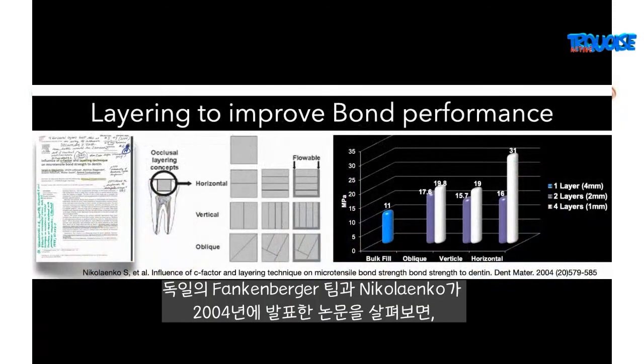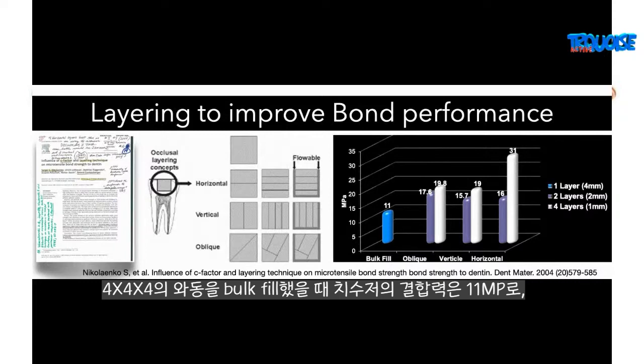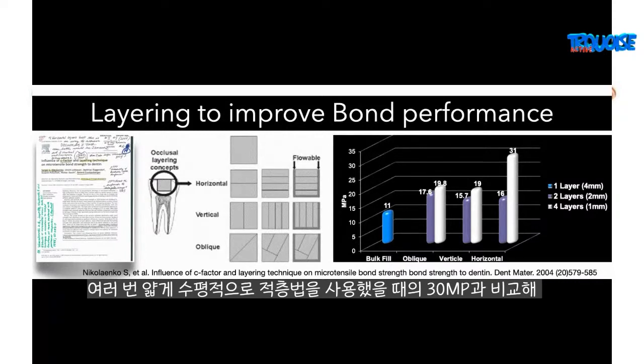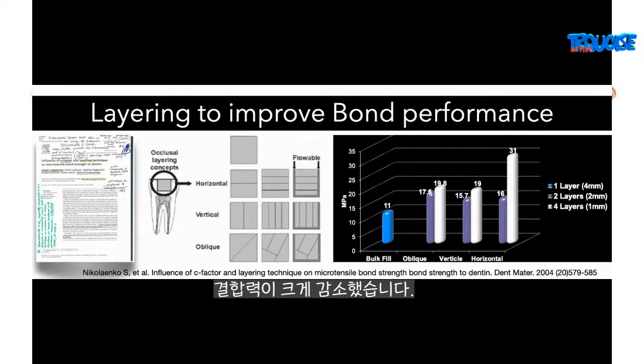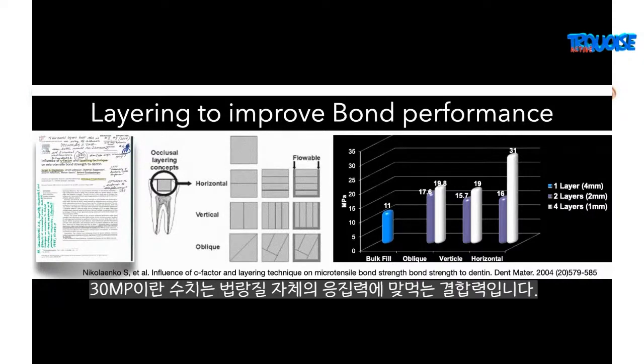So the paper that was published in 2004 by Nikolenko and Frankenberger's team in Germany showed that bulk filling a 4x4x4 preparation will decrease the bond in the pulpal floor to 11 megapascals, compared to a layering technique of multiple thin horizontal layers, which will go to over 30 megapascals. And so 30 megapascals is close. It actually is the average cohesive strength of enamel.